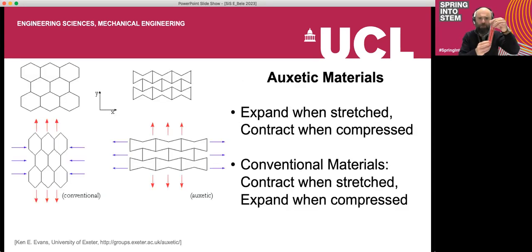How about making materials for unique properties? As you might expect, when we stretch a material it wants to conserve volume. We stretch it up and down, and left and right it becomes small. When we compress it, it becomes bigger to conserve volume. That's a conventional material. A class called auxetic material has the complete opposite property. When you stretch it, it becomes larger in the transverse direction. When you compress it, it becomes smaller.